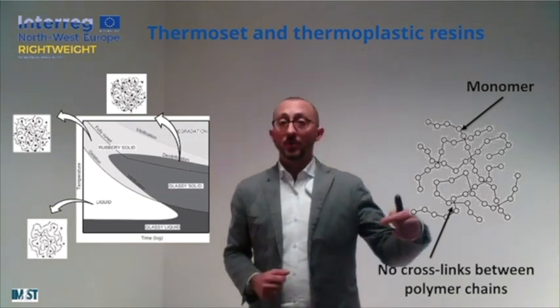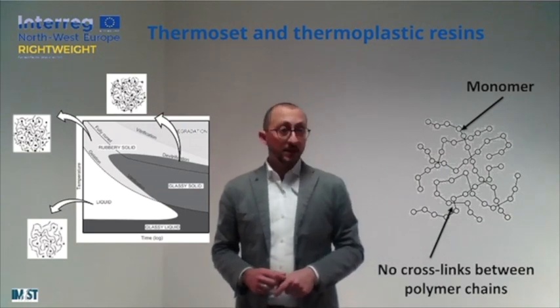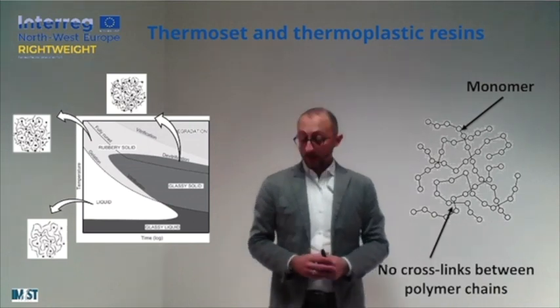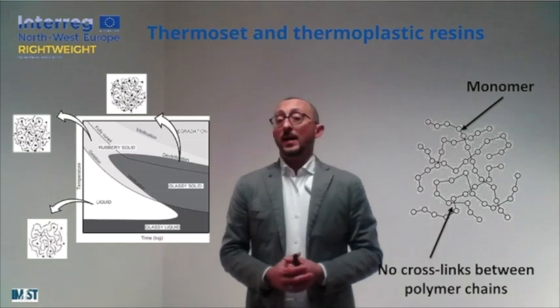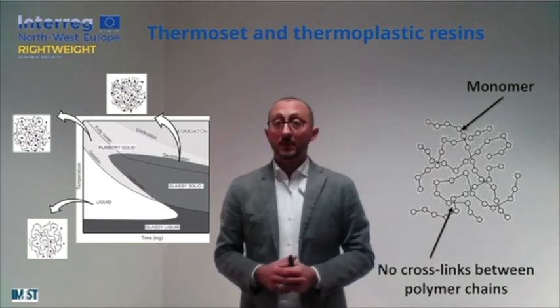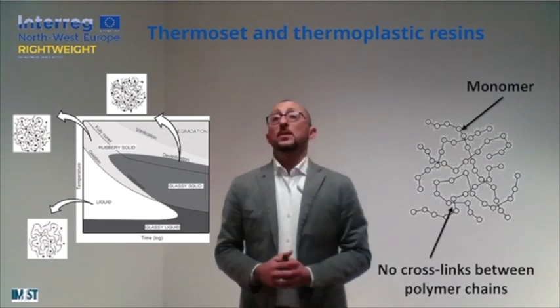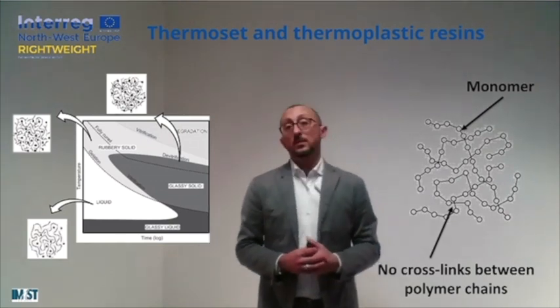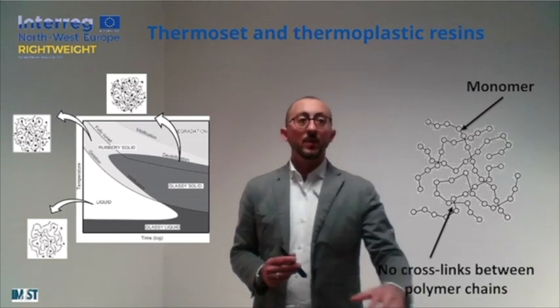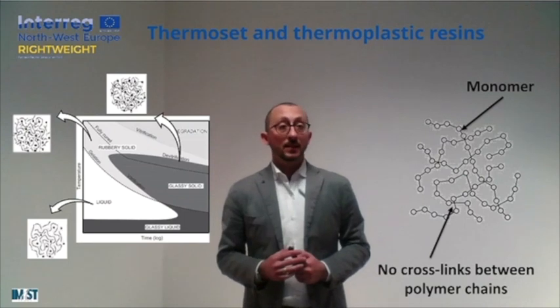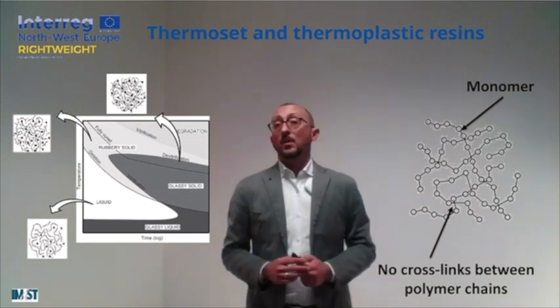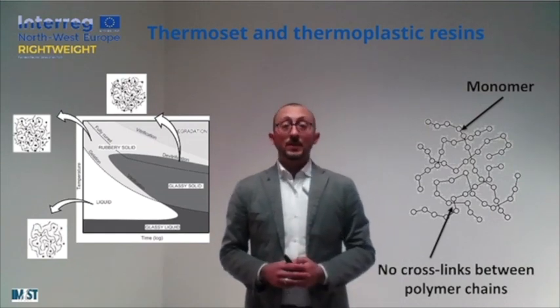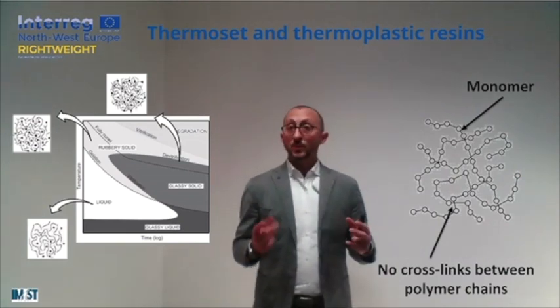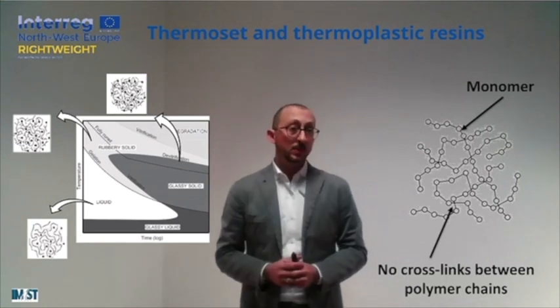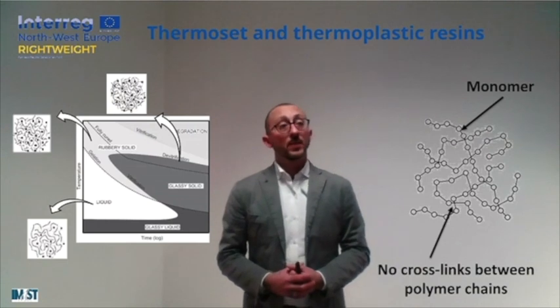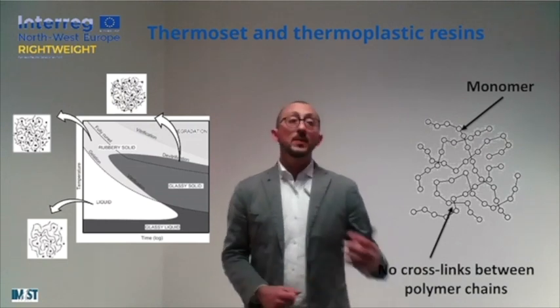But the reaction will keep on going, and the degree of cure will increase if the temperature is a suitable one. Increasing the degree of cure will improve the mechanical properties of our material, and the second phase change that we can promote during this curing reaction, and most probably it will happen when we are cooling down our material, is the so-called glass transition or vitrification. In correspondence of this transition, that is sensitive to both degree of cure and temperature, so we don't have just one value of degree of cure for this kind of transition, the status of our material will change from rubbery to a vitrified solid.